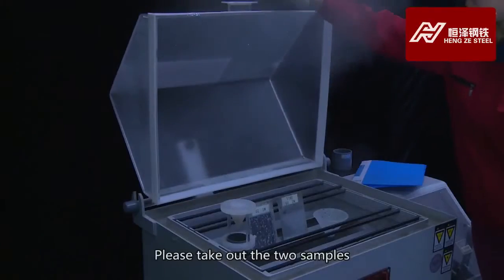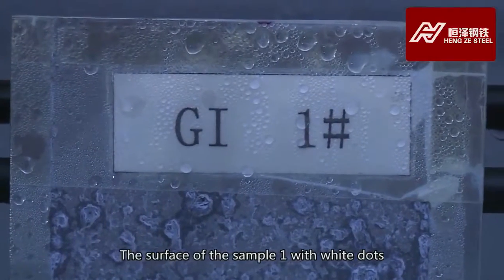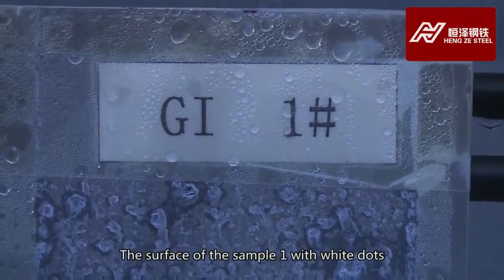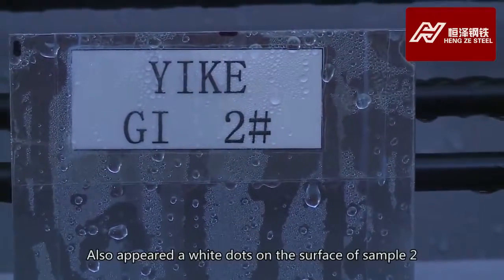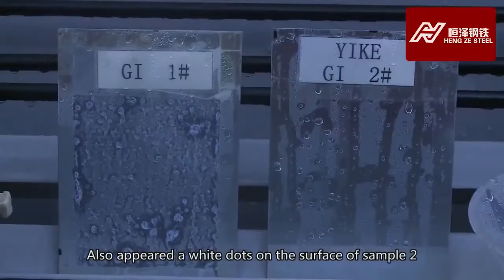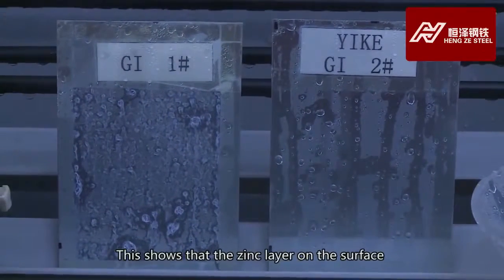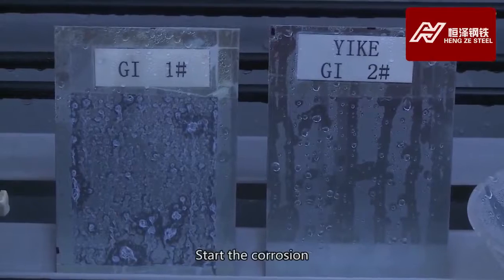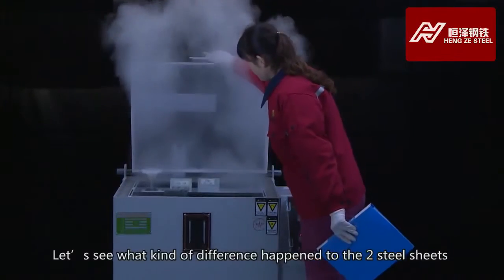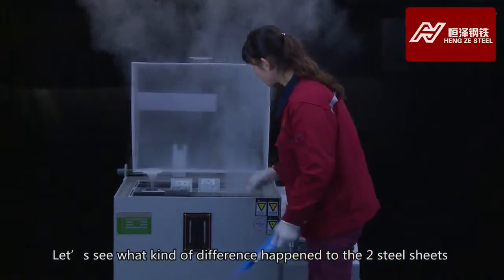Please take out the 2 samples. The surface of sample 1 shows white rust. The surface of sample 2 is excellent, without damage. This shows that the zinc layer on the surface of sample 1 has started to corrode. Let's see what kind of difference happened to the 2 steel sheets.